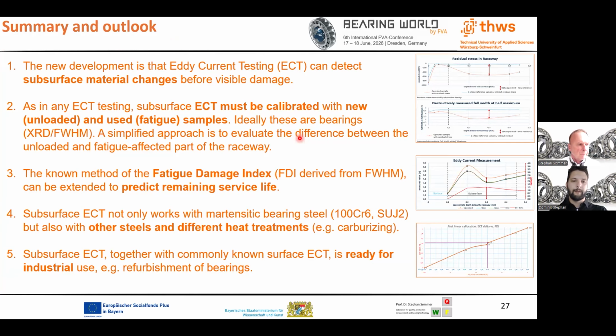To summarize, the new development is that eddy current testing can detect subsurface material changes before visible damage occurs. As in every ECT application, the method must be calibrated. For subsurface ECT, this requires new unloaded samples and used fatigue-affected samples. Ideally, these are complete bearing samples with destructive X-ray reference data.